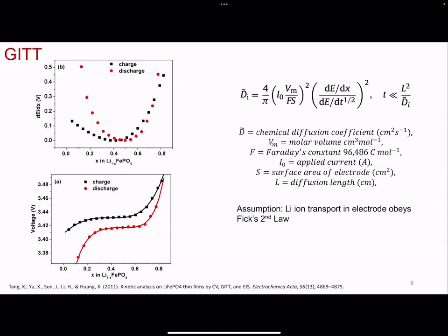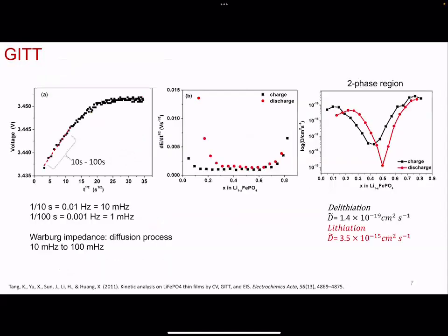Okay, great. So to get dE/dx, you measure the OCV, you lithiate, measure the OCV, and you can plot all of that for lithiation and delithiation, or discharge and charge, and you get the dE/dx plot. So you get those values that way. You could also get the dE/dt in the same way.